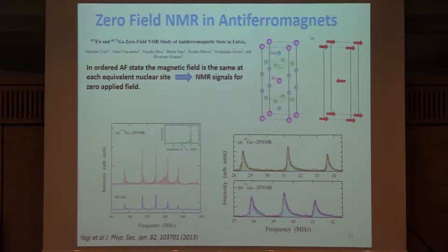And in a paramagnetic material, you'd see nothing. But here, you see very distinct absorption peaks, and they've got multiplets associated with a particular nuclear structure. So you can actually see characteristic nuclear magnetic resonance, and you can associate them with particular atoms, types of atoms, out of this structure. The reason you can see it is the antiferromagnetic order. So every equivalent site is sitting in the same field. Okay? It's not disordered. So if you can see this sort of signal, then you can infer what the strength of magnetic fields are at the nuclei, and the symmetry of magnetic fields at the nuclei.